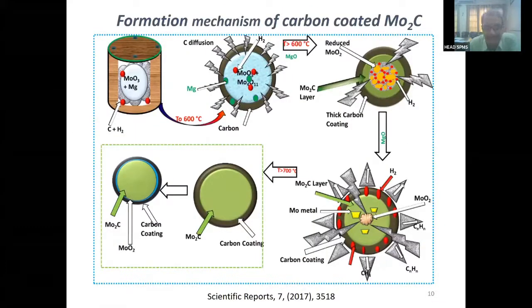This is the mechanism. I have already told you what occurs inside the autoclave, and this is the important part. You can see that initially there is a carbon coating on the surface, and slowly it becomes thicker and thicker, and at the interface of the material, the elimination of oxygen takes place and carbon is deposited over here. Inside, this is the core part. You will see that molybdenum oxide exists, and hydrogen penetrates slowly along the grain boundary, and an Mo2C layer forms inside. This is the mechanism which we have reported in Scientific Reports, a Nature group publication.